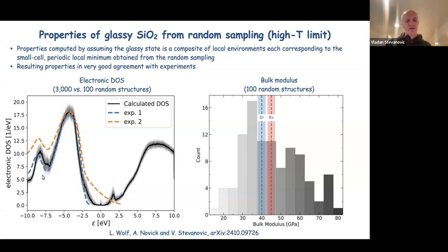All right. So in order to really enable high accuracy calculations, you really cannot do GW on 3000 structures. So we did a follow-up exercise where we took the 3000 result as a reference, and then picked randomly 100 of those and saw how well the average density of states is reproduced by averaging over just a sample of 100. We did this 100 times. The gray band that you see around the black is the 100 curves, each evaluated as the average over a sample of 100 structures. Again, we don't see a big deviation from the reference, from the black.